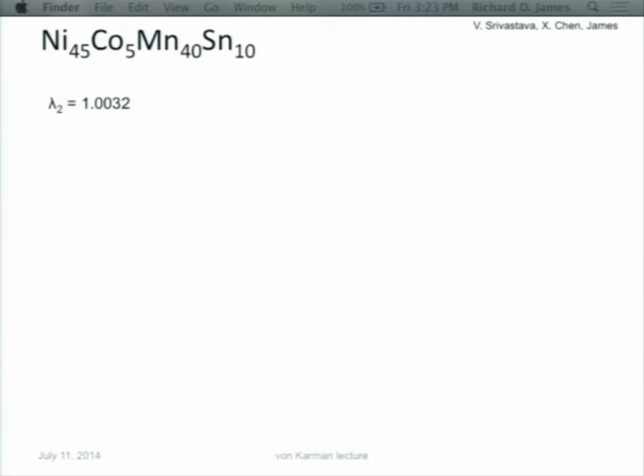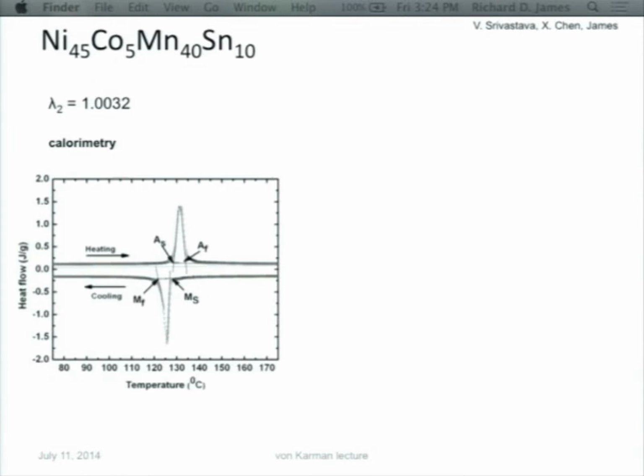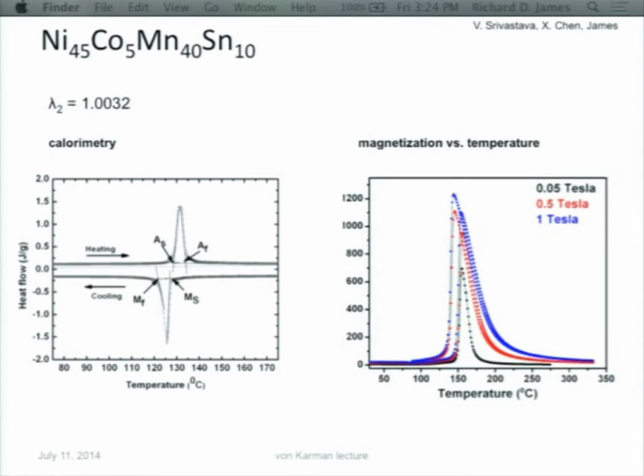We used it in a family of alloys called Heusler alloys, this is a perturbation of a Heusler alloy. Heusler alloys are famous because they have a great propensity toward ferromagnetism. So in fact, in this alloy, we changed composition and we got the middle eigenvalue this close to 1. We could do better, of course. But it's got about 6 degrees hysteresis, and it's got a transformation temperature, this is calorimetry, of around 135 degrees C. But what's interesting about this alloy is that the low temperature phase is non-magnetic, but the high temperature phase is magnetic.